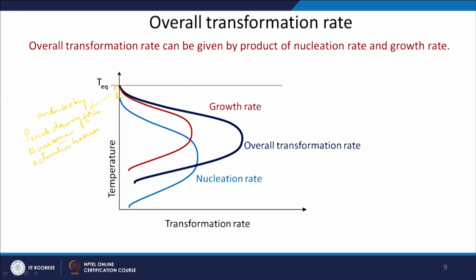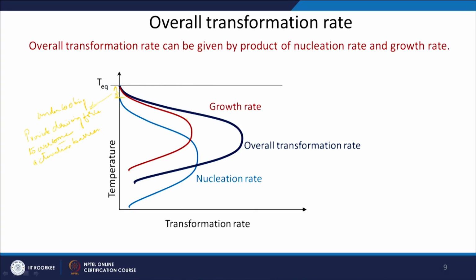So, this is your nucleation kinetics. Initially there will be some undercooling. As you bring down the temperature, the nucleation rate will increase, because now you are giving more driving force. As you keep on decreasing the temperature, the driving force will increase, but it will saturate at a certain temperature, and then the nucleation rate will start decreasing, because the diffusion of atoms, which is required to make the nuclei stable, becomes very slow. So, again it will come down. Similarly, the growth rate will also increase as you bring down the temperature, then it saturates, and again as the diffusion becomes slower, the growth rate will also decrease.